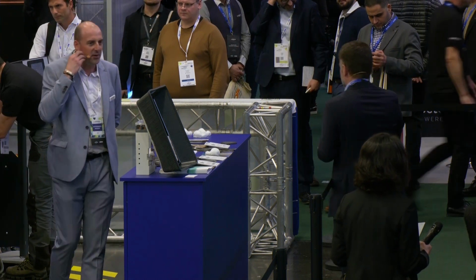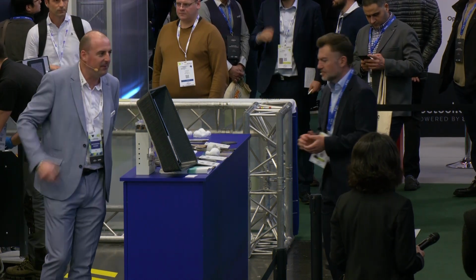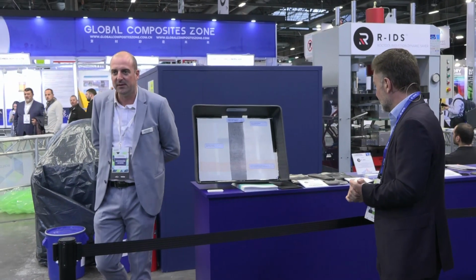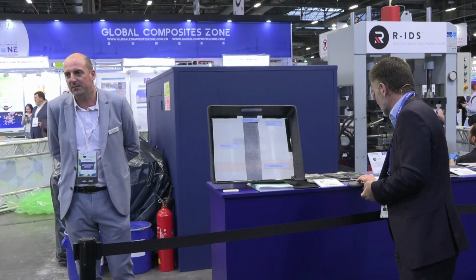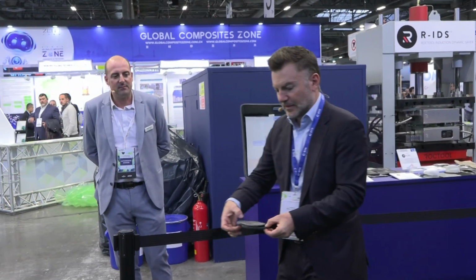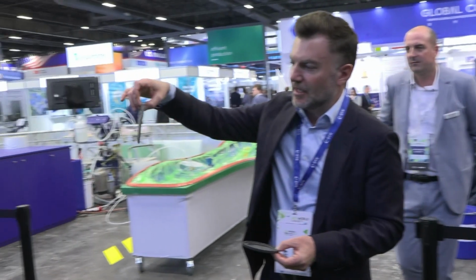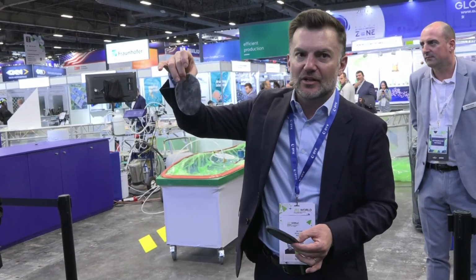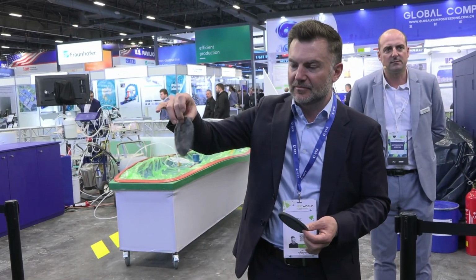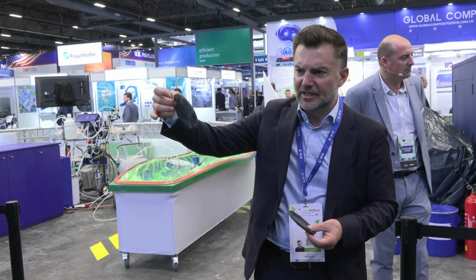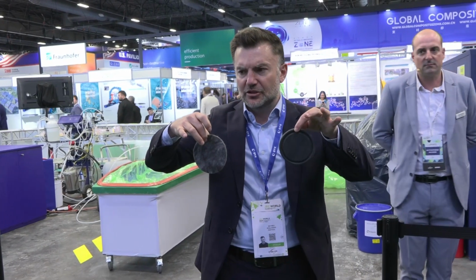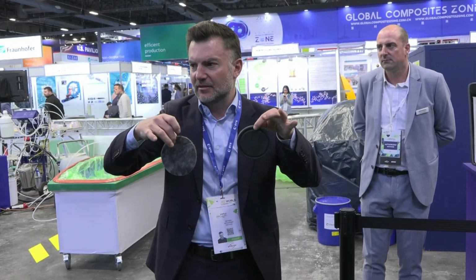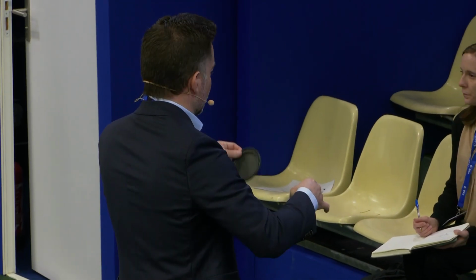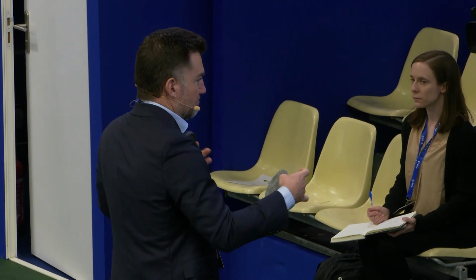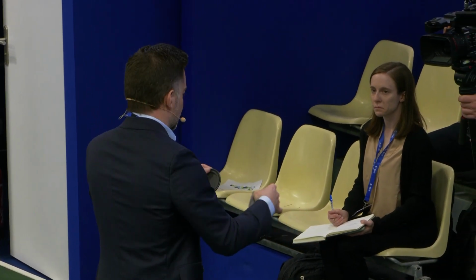In this configuration, we reach a heating ramp around 55 degrees per minute and around 60 degrees per minute for the cooling. Here's an example of 100% recycled carbon as non-woven with pre-impregnation of, I think, polypropylene in this case, and how you can transform it with just a 5-minute cycle time, using a small aluminum insert, so a very cheap mold, using the heated platen.